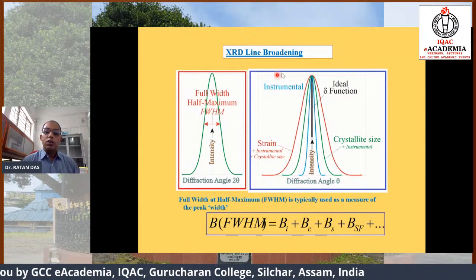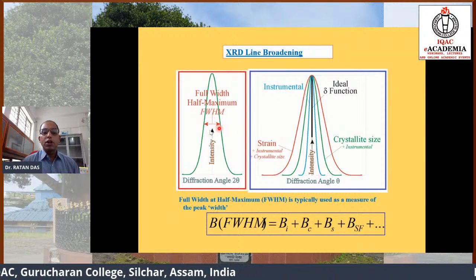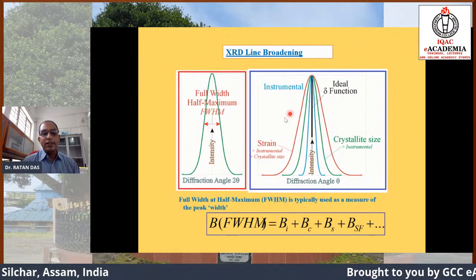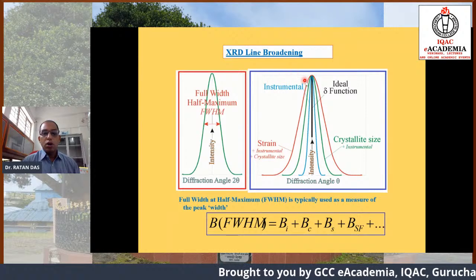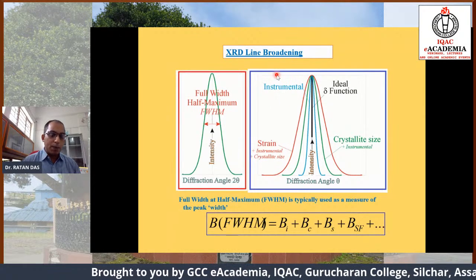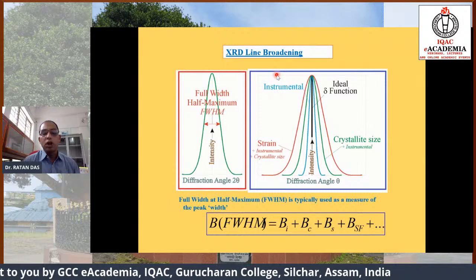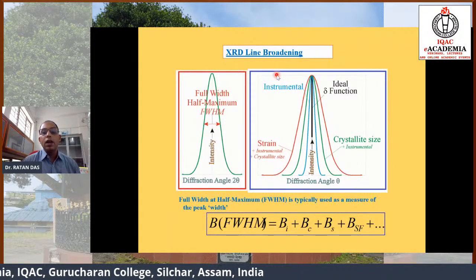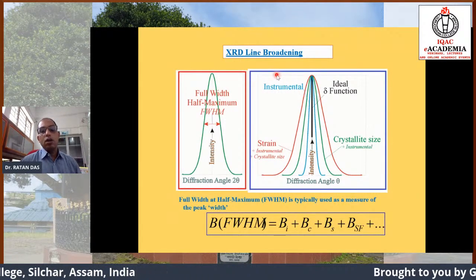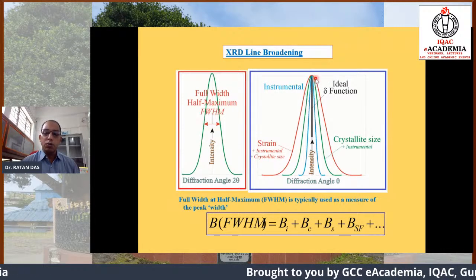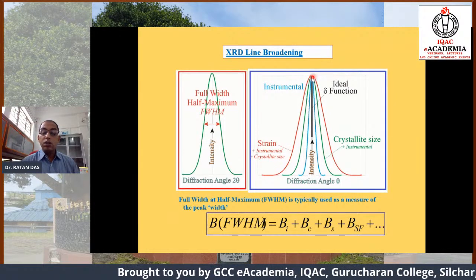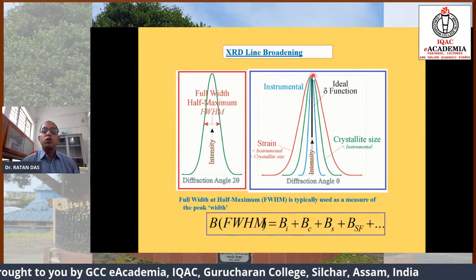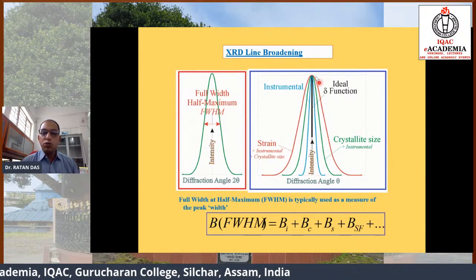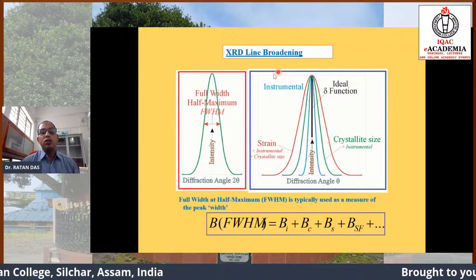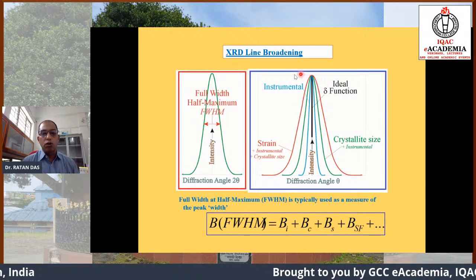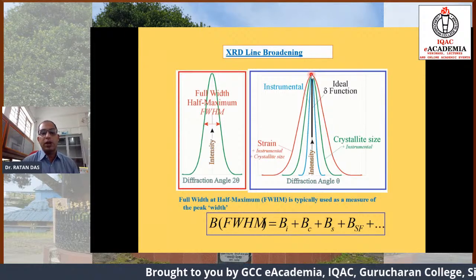But the instrument plays a role in broadening the diffraction pattern, what is known as instrumental broadening. So if you take an X-ray diffraction pattern of a bulk sample, there may be a chance that you obtain some width in a particular peak. This generally happens because of the instrument, because we need to calibrate the instrument. The instrument plays a role in broadening the X-ray diffraction pattern.